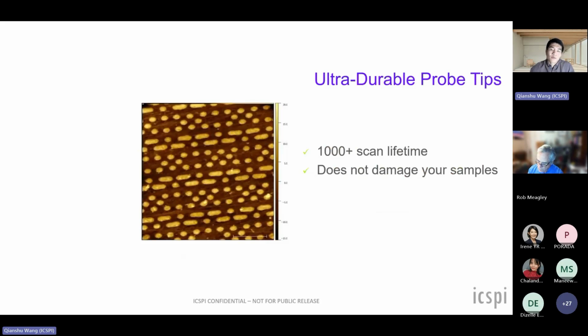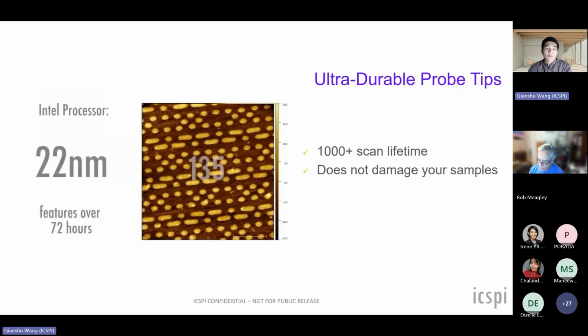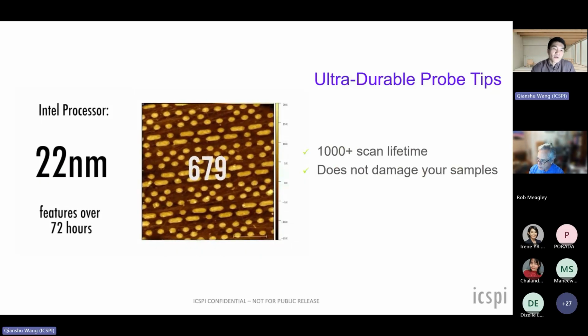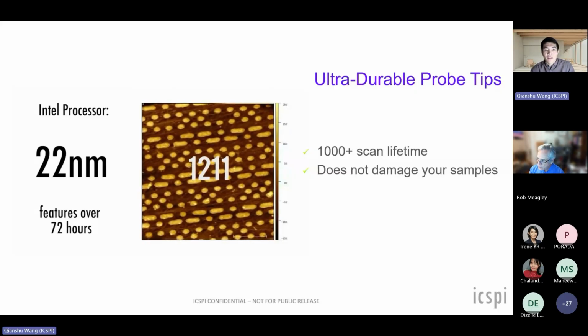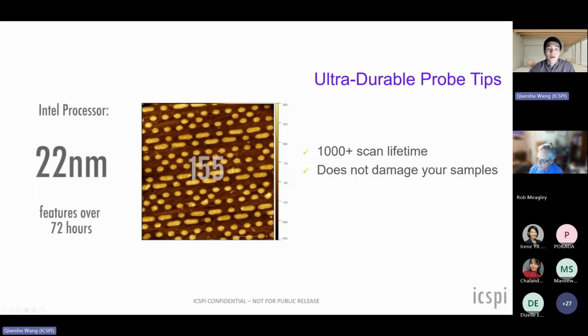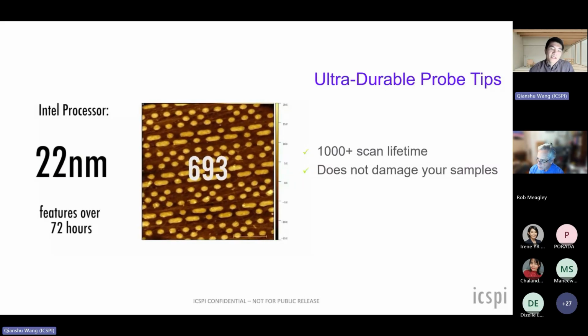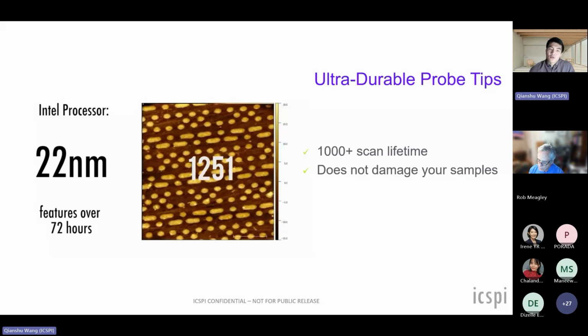Traditionally, AFM probe tips will usually last you about 1 to 2 dozen scans, and they typically blunt out. Because of the contact forces involved, they essentially get too blunt to be able to image well. Now, shown here is one of our AFM probe lifetime tests. We're scanning 22 nanometer features on an Intel processor. These scans are taken over 72 hours, and you'll see in here that the number is incrementing. This is the total number of scans. You're able to see that we managed to take up to almost 1,250 scans, and we see no dilation of features.